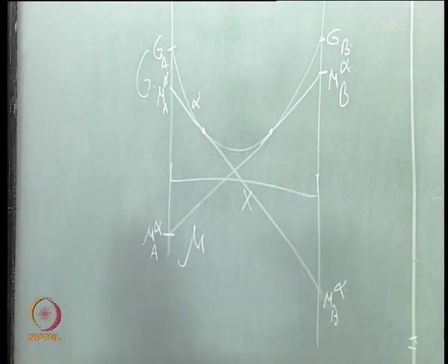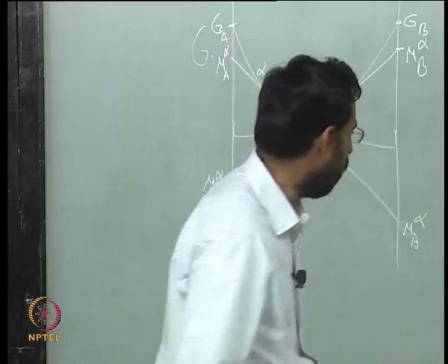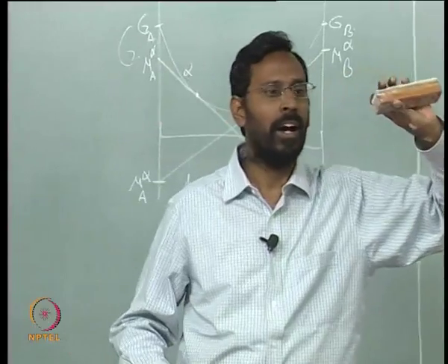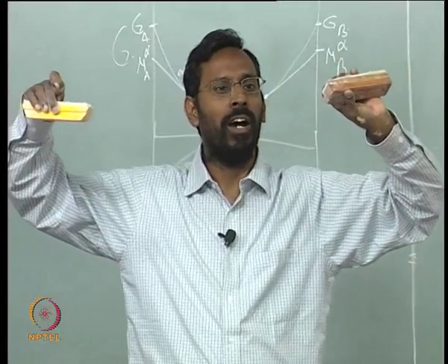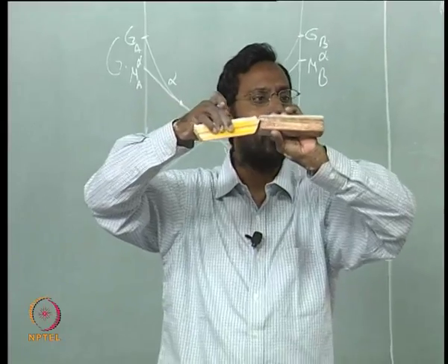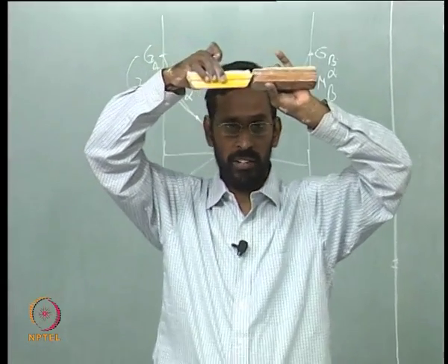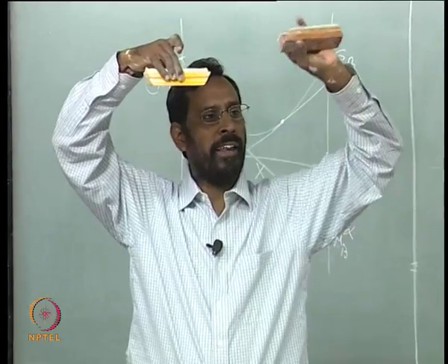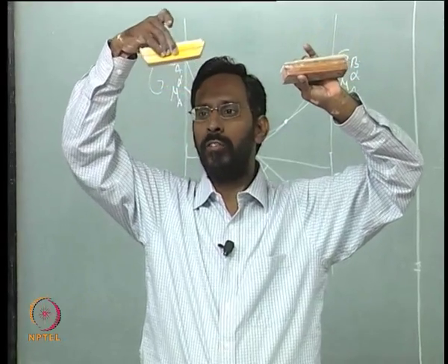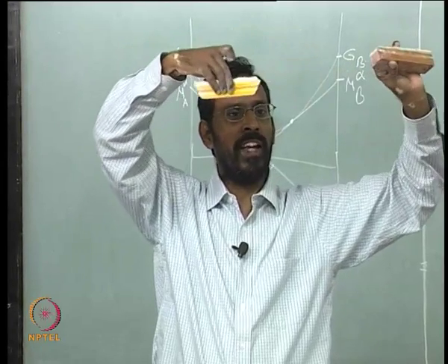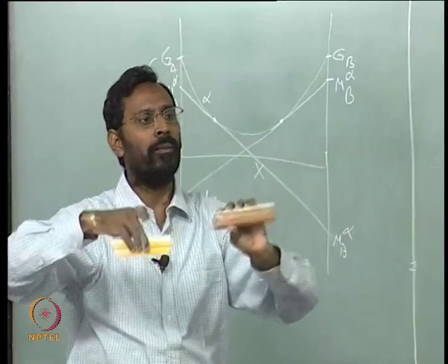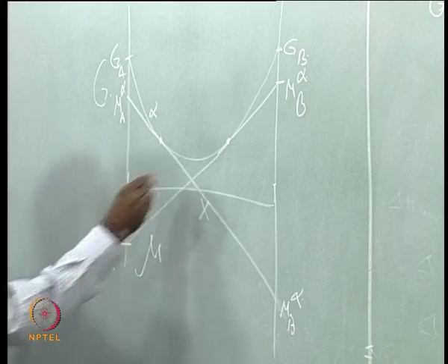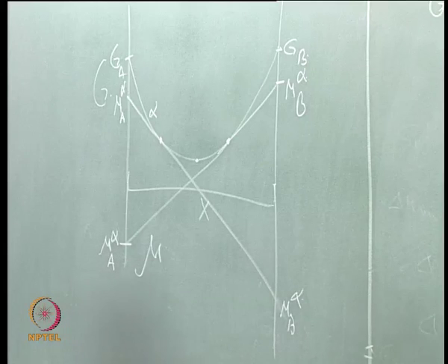So, in principle, if I bring two pieces of alpha, let us say one has 30% of zinc, whatever it is, B element, and one has 70% of B element, weld them together and hold them at that particular temperature as a function of time, you would see, because one has B atoms being more active and another has A atoms being more active, that B atoms will diffuse towards this side and A atoms will diffuse from this to this, and both will come to an equilibrium at some stage, so that the composition of both pieces becomes the same, some equilibrium composition.